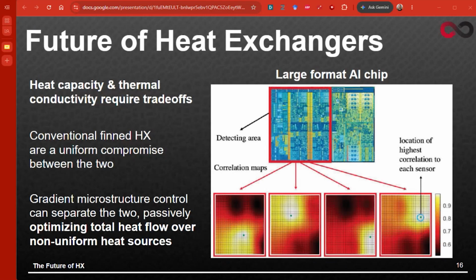On the next slide, we want to mention also, because it's in the drinking supply, AI, right? Some of these massive chips now that are being touted on stage, they don't actually release heat evenly. Some sections of the chip may release a lot more heat than others. And so when you put a homogeneous finned heat exchanger on top of them, it's not as efficient as it could be because you're trying to apply a uniform solution onto a non-uniform problem. But we can produce a heat exchanger which is thicker or not as thick, more sparse in sections, in order to move that heat most effectively from the uneven source to an even cooling sink.